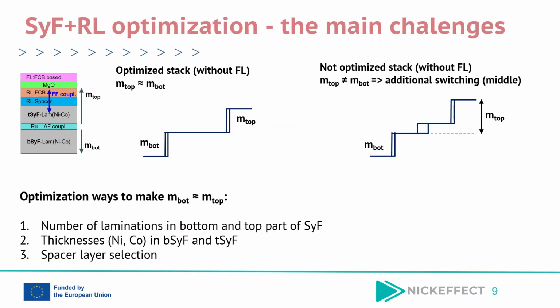In practical MTJ structures, the top part of the synthetic ferrimagnet, tSyF, is ferromagnetically coupled to the reference layer RL of the tunnel junction through their properly optimized RL spacer. Strong coupling between the tSyF and RL is crucial for stabilizing the reference layer and preventing independent RL reversal. The main design challenge is to obtain a well-compensated SyF structure for which the magnetic moments of the bottom and top SyF parts are almost equal.